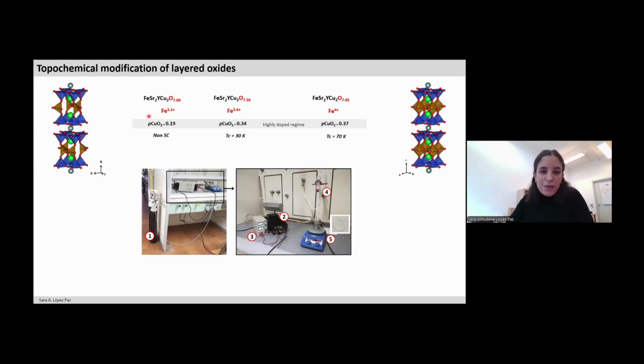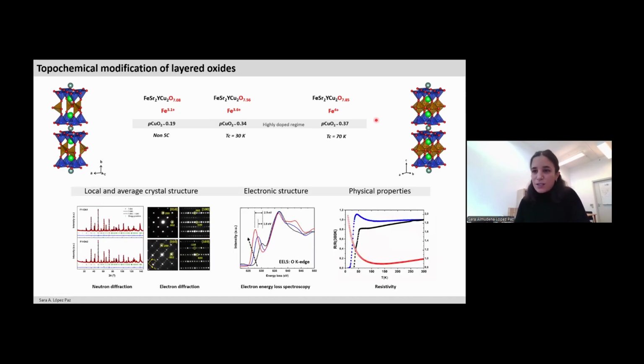And I think you can realize that I'm putting here very precise numbers for the oxidation states and for the oxygen content. And this actually comes from a very detailed characterization of both the crystal structure at the local and average range, also of the electronic structure, for example, by looking directly at the amount of holes that we have at the oxygen atoms, and through a measurement of the physical properties, where we can actually see how we can go from an insulating material to a superconducting material, which actually shows zero resistance.